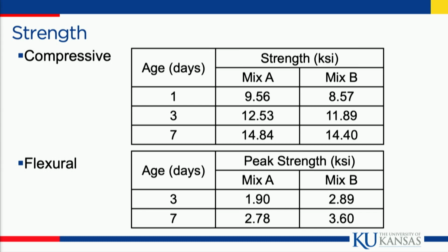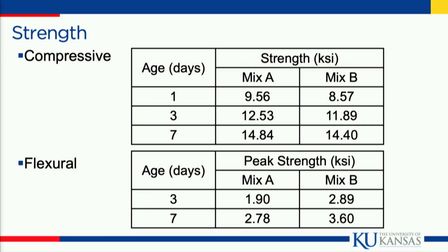We also looked at the compressive strengths that we got at 1, 3, and 7 days. We looked very hard at the 7-day strength. You see a little bit higher strength for mix A, but mix B catches up around 7 days. And the flexural capacity was really high, especially mix B with the better distribution of fibers. Okay, so bond, and let me back up. Here, notice that we're talking at 7 days, 3,600 PSI in tension. That's pretty hefty stuff. Okay, bond tests.